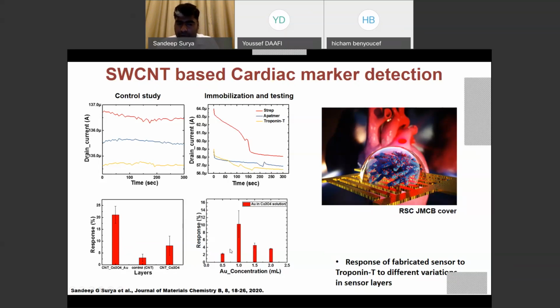And apart from that, we have also made a study of how much gold loading on top of cobalt oxide nanorods is important in order to come up with a very precise optimized value of sensitivity. So here what you see is that around 1 ml of gold loading on top of the cobalt oxide nanorod solution will give proper and high sensitivity when it comes to detection of troponin T.